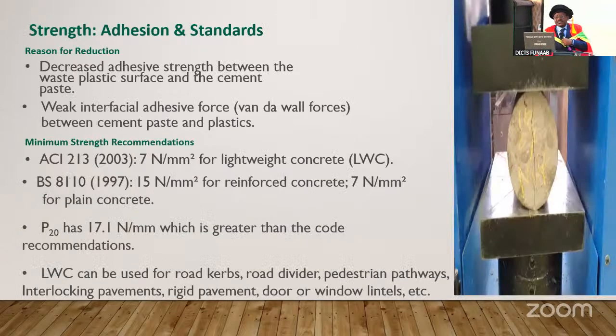Now, we look at what the code is saying. According to ACI 213, like I quoted the other time, 7, 15, and 7. And the lowest we have here is 17.1, which shows that what we have is greater than the recommendation of the code. That is, we can use this plastic waste, but not greater than 15% in our concrete. So lightweight concrete can be used for road curbs, road dividers, pedestrian pathways, interlocking pavement, rigid pavement, door and window lintels. The lintel of your window and house, we can use this plastic waste for it when we mix it with concrete at that percentage.